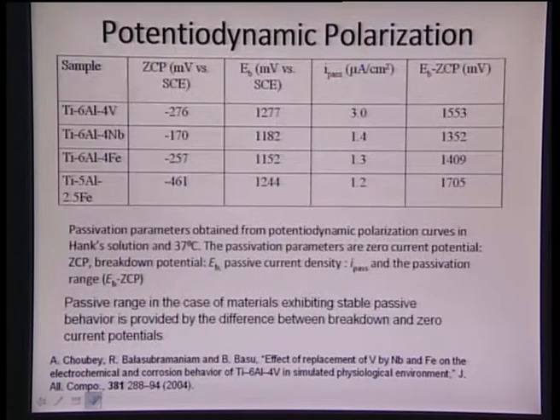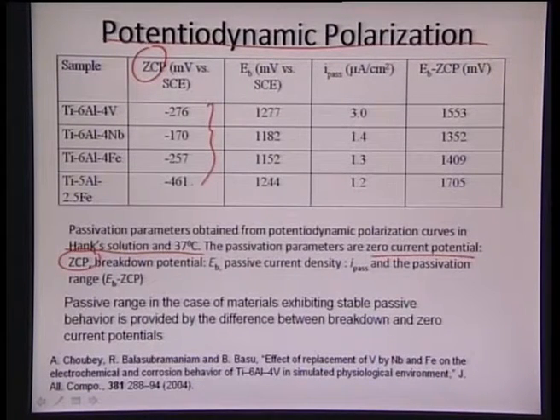And coming back to the corrosion part of it, the passivation parameters were obtained from the potentiodynamic polarization studies. They were done again in the Hanks solution at 37 degrees centigrade, and they found out the passivation behavior around the zero current potential, which was ZCP, and they saw various values for the different titanium alloys. And the region between the breakdown potential and the zero current potential is the regime where the material remains much more stable or passive. So that stable passive region is defined in the region between the zero current potential and the breakdown potential. So in this, if we just draw a comparison of all these 4, we can realize which material is basically much more stable in nature.